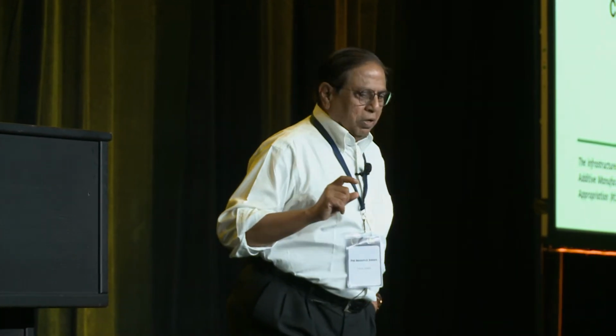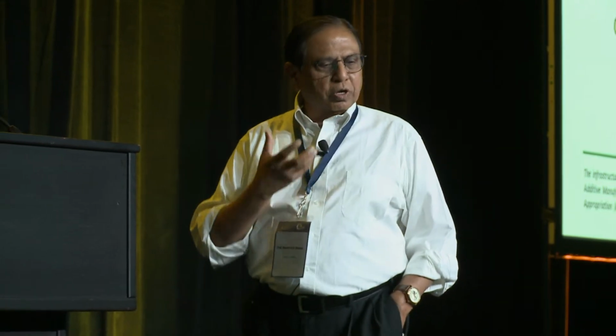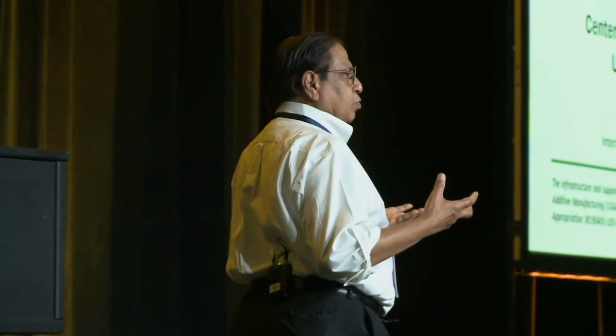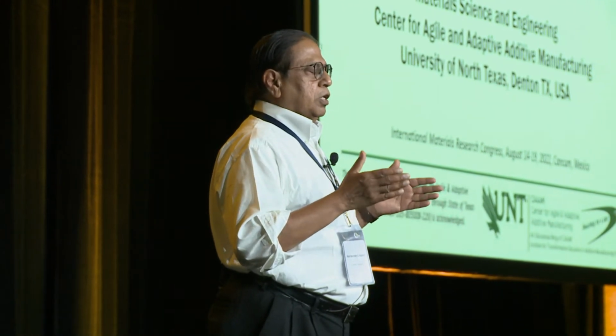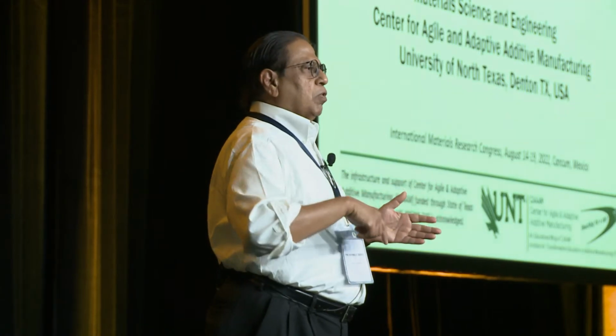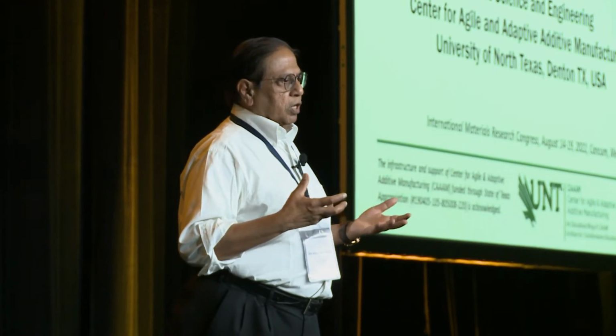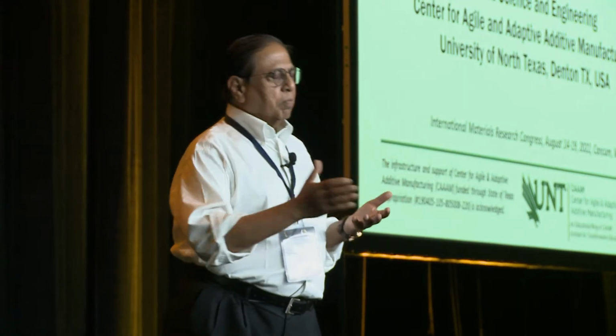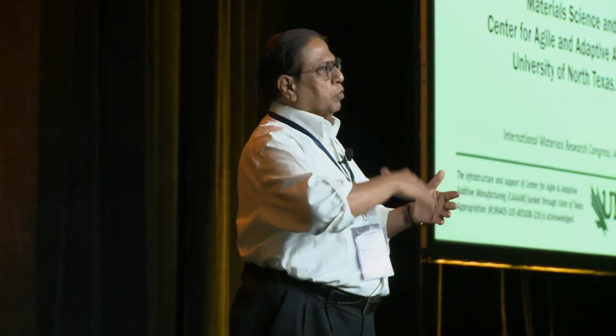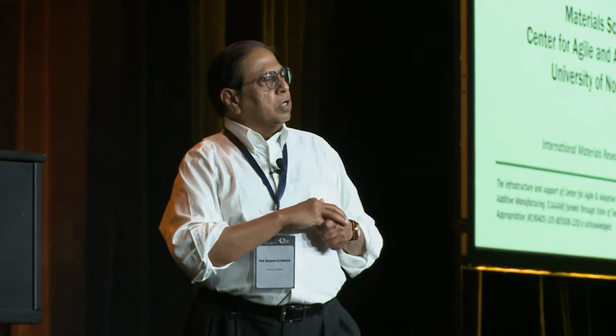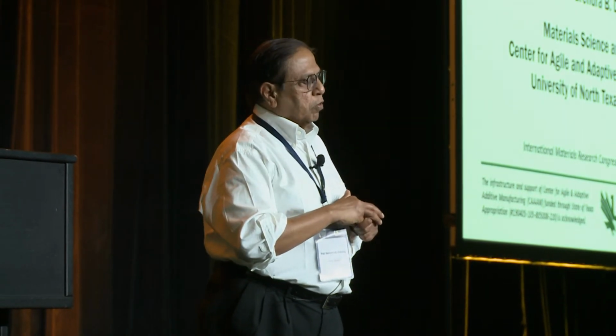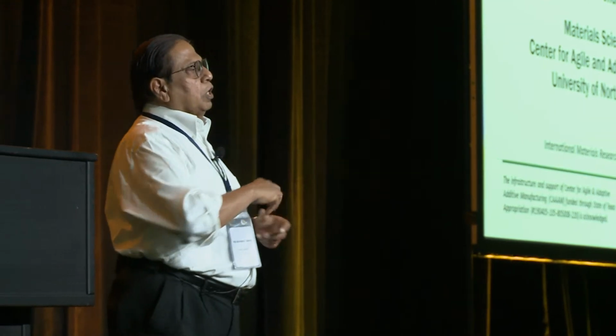And now again, I have to give one more background before I start showing you my slides. It's very important to have some background. As I said a minute ago, additive manufacturing is mostly a laser-based process, the powder bed fusion process and the powder injection process, the directed energy deposition process. In one process, we have a powder bed, the powder set in the tray, and the laser beam comes and moves onto the powder, and the powder gets fused. The fused powder gets covered by loose powder. Again, you move the laser beam on it, and you can build a component layer by layer. So the powder is stationary in this laser powder bed process. Powder is stationary, only the laser beam moves.